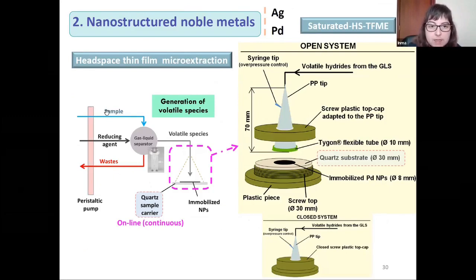As we can see in the slide, this is the scheme that we follow. We have a gas-liquid separator, peristaltic pumps, and different tubes. One tube is used for the sample introduction into the gas-liquid separator. And then we have another tube with the reducing agent, which is usually sodium borohydride in presence of sodium hydroxide to stabilize the solution. It is important to remark that the sample solution has to be a high concentration of hydrochloric acid, usually 5 or 10% volume. Then in this gas-liquid separator, we use argon as a carrier gas that moves these hydrides or mercury vapor generated from this gas-liquid separator to the part where the nanoparticles are immobilized into the sample carrier with another tube. And this is a closed system that we can see in a detailed scheme in the figure on the right.